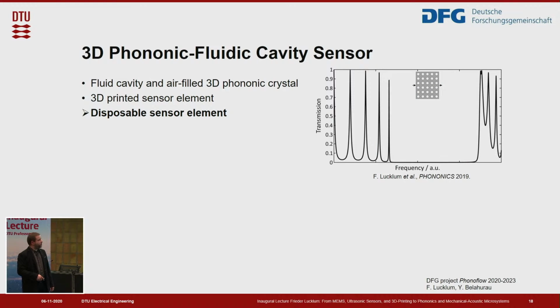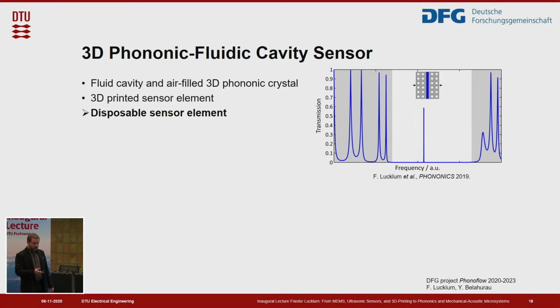The concept of this cavity resonator and this cavity sensor is as follows. We start with the phononic crystal, and this defect resonance is directly dependent on the properties of the liquid inside the cavity. So changing the liquid changes the resonance frequency. And therefore we have direct access to the bulk properties, especially to the speed of sound, density and compressibility, and also viscosity of the liquid that we want to analyze.